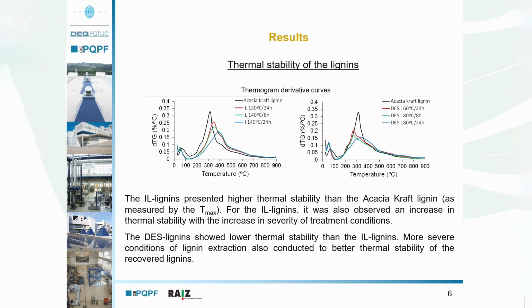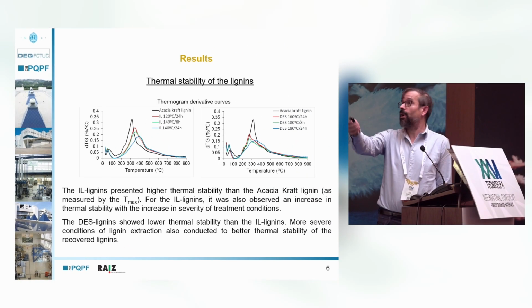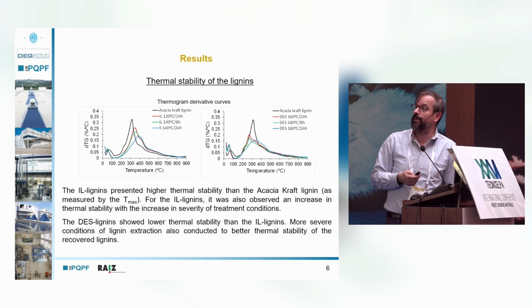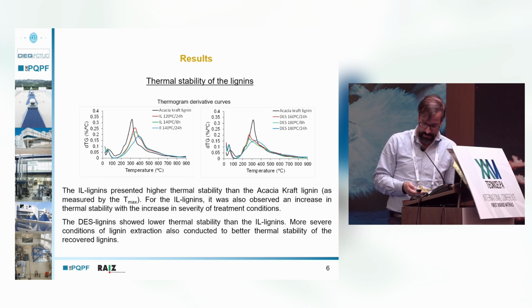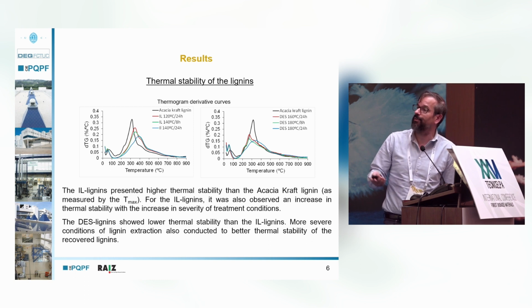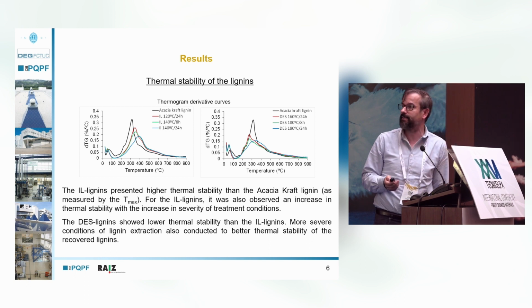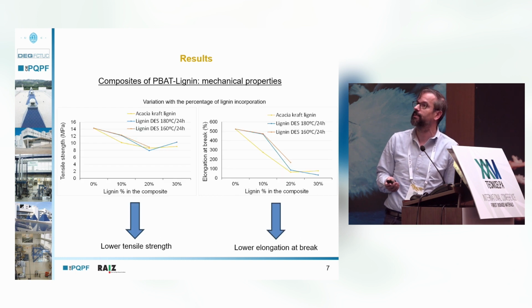The ionic liquid lignins also show an increase in thermal stability with increase in severity of treatment conditions. So if you use higher temperatures and longer extraction times, you can obtain lignins more thermally stable. As for the lignins extracted with eutectic solvent, these show lower thermal stability than the ionic liquid lignins, but again, more severe conditions of lignin extraction also lead to better thermal stability of the recovered lignins.